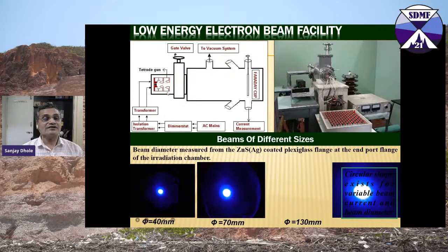This is a tetrode type electron gun, from where you can have the electron beam coming over here and fall on the Faraday cup. So this is the setup, and you can have beams of different sizes. If you change the voltage at the anode, then you can have different sizes of the beam. You can have 4 cm, 7 cm, 13 cm. So even a large number of nanophosphors, you can put together and expose with the low energy electron.